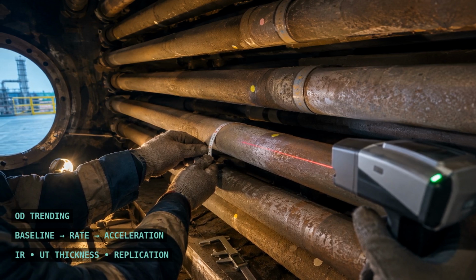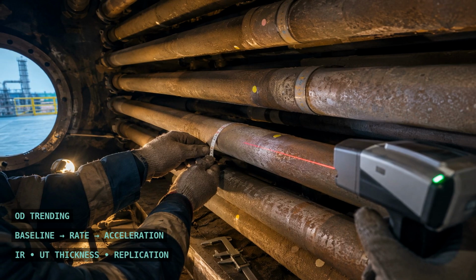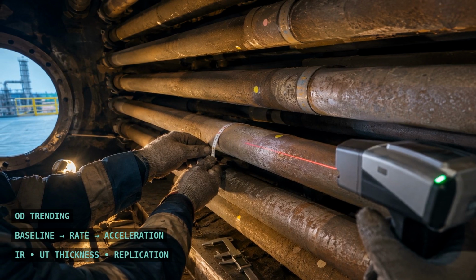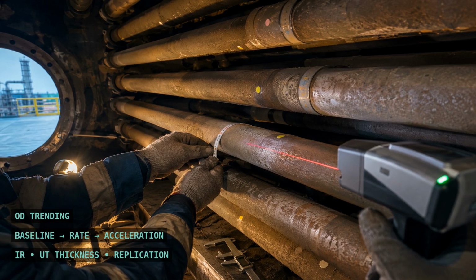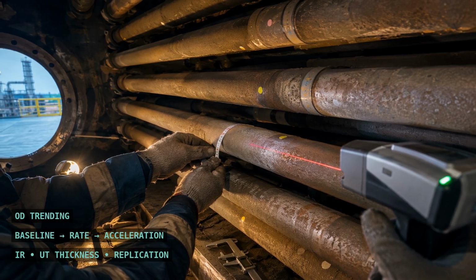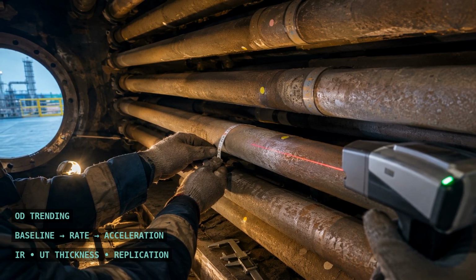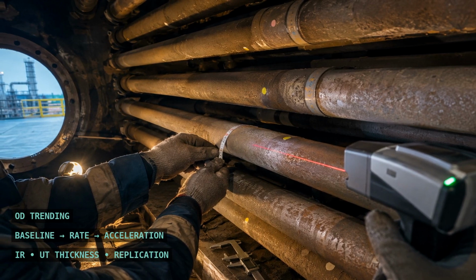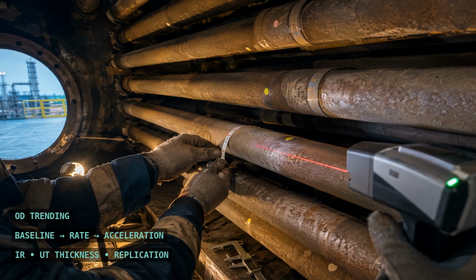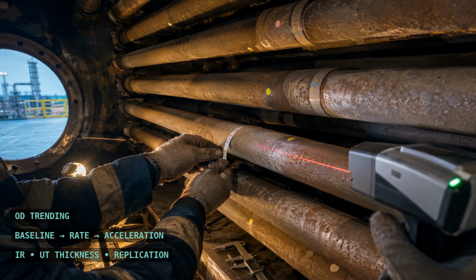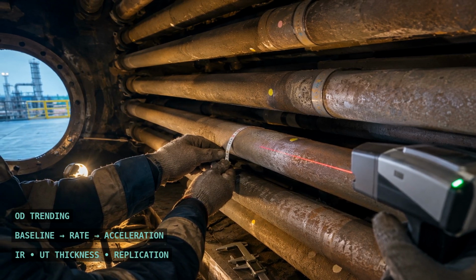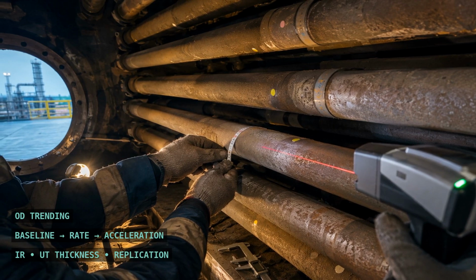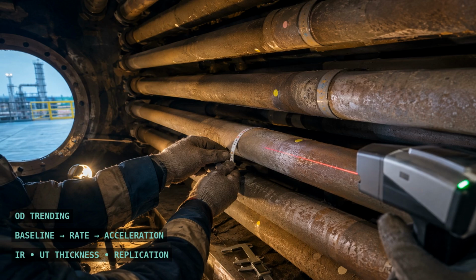Infrared thermography finds hotspots on operating tubes directly. Ultrasonic thickness readings quantify the local thinning. Hardness testing and field metallography, surface replication, reveal how far the internal microstructural damage has actually progressed. Shape, temperature, thickness, and microstructure. Together, they turn a bulge into evidence.